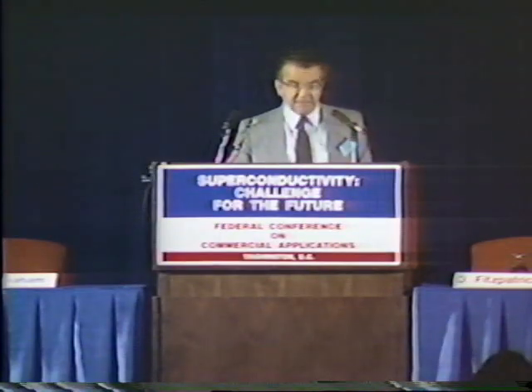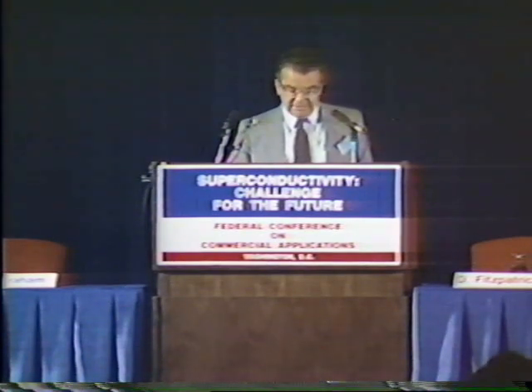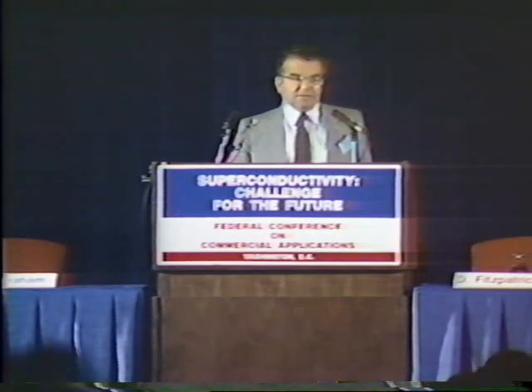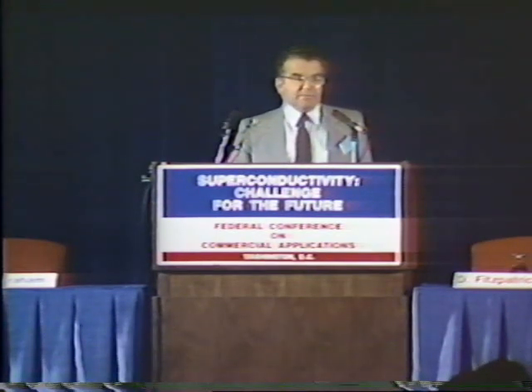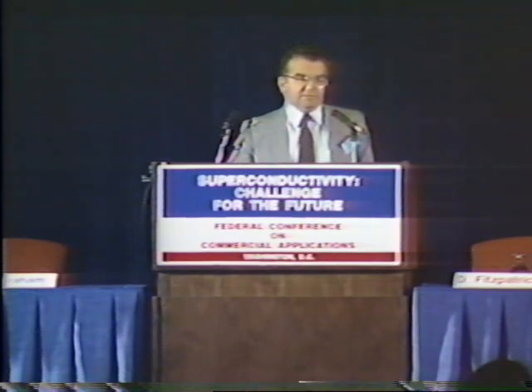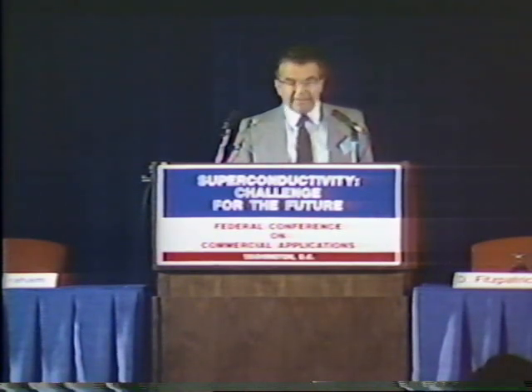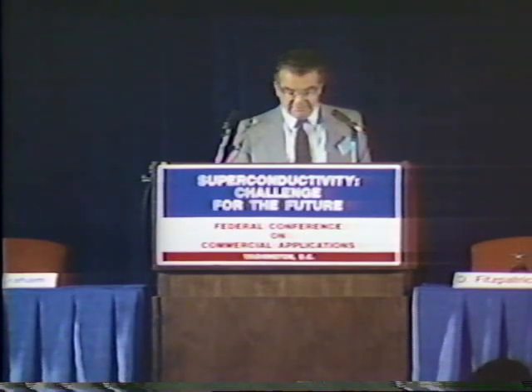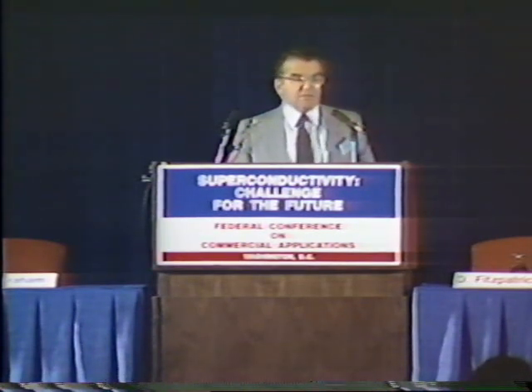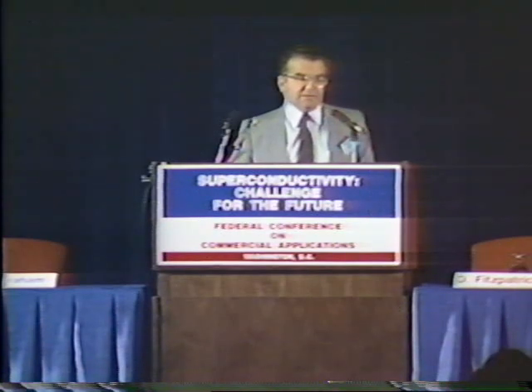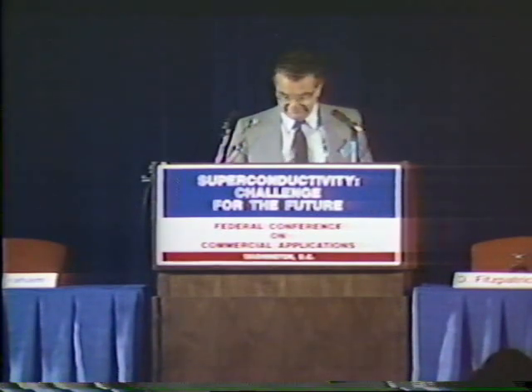Now, the other extreme, I think, is a technique which we discussed recently at Bellcore, where you just take a target of the already pre-reacted material, in fact, the superconducting material, and you impinge on it a pulsed laser beam. Every time a pulse hits it, you get a plume of material ejected from the surface, which you can collect, again, on a substrate at, say, 500 degrees. The technique is simple, it's cheap, doesn't require very good vacuum. In fact, the first films we made were made in air in the room by just holding a target in front of the beam with a substrate nearby.